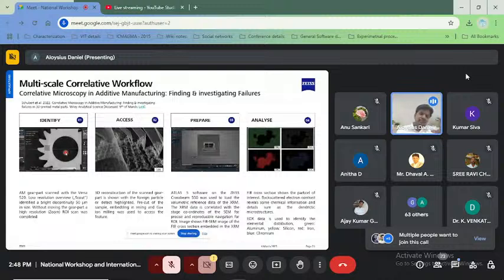So this complete workflow enables them to inspect the complete component and very precisely understand where there are unsintered particles, because it is laser sintering, right? Where there are unsintered or satellite particles, where you observe some voids or cracks. All this can be done, and in this particular example, what they found is contaminations in the sample that was manufactured through additive manufacturing. So you can see here it had iron and chrome in, I think, a titanium gear, and they found contaminations of iron and chromium in one particular region, which was identified non-destructively, and then it was taken down until we were able to have the complete analytical information.